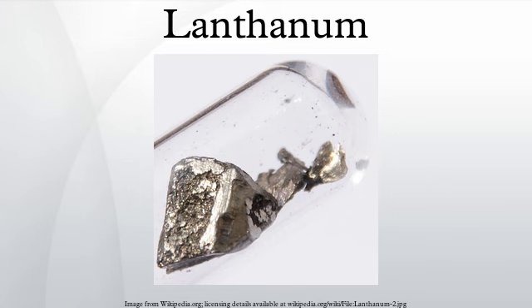The fractional crystallization purification of lanthanum as the double ammonium nitrate was sufficiently rapid and efficient that lanthanum purified in this manner was not expensive. The Lindsay Chemical Division of American Potash and Chemical Corporation, for a while the largest producer of rare earths in the world, in a price list dated October 1, 1958 priced 99.9% lanthanum ammonium nitrate at $3.15 per pound, or $1.93 per pound in 50-pound quantities. The corresponding oxide was priced at $11.70 or $7.15 per pound for the two quantity ranges. The price for their purest grade of oxide was $21.60 and $13.20, respectively.